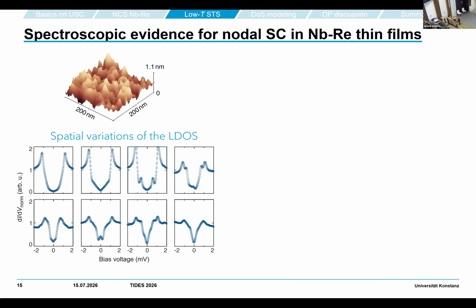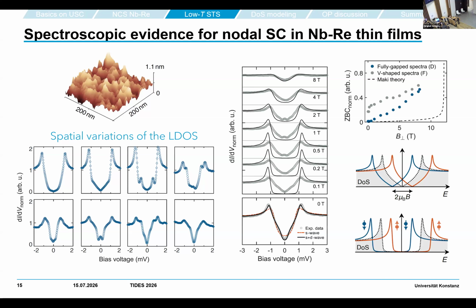However, this is not the only possibility. There are also statistically significant spots where we see deviations from this S-wave geometry. Here you see a selection out of many spectra we took - more rounded spectra that are not fully gapped anymore, with V-shaped characters. We can have in-gap states, and also something that looks really like P-wave, these V-shaped spectra with double peaks, which we can follow as a function of magnetic field.